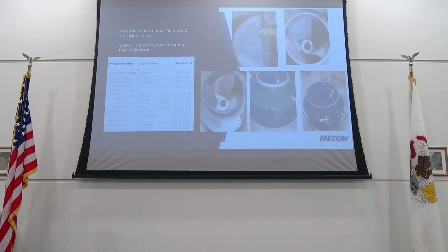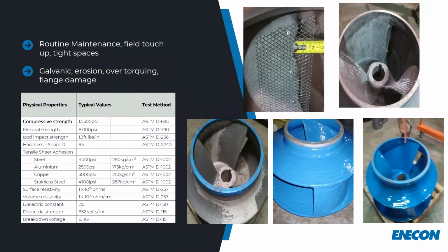But something I wanted to show you guys here, this is just a pretty good coating system here, is where you see the compressive strength, 13,000, very strong. On a 2-component system, your hardness is pretty good there. But the biggest thing I want to show you, this isn't showing up too well, but the adhesion. That's always a big deal when you're looking at this. That 4,000 PSI adhesion to blasted metal is very, very high.